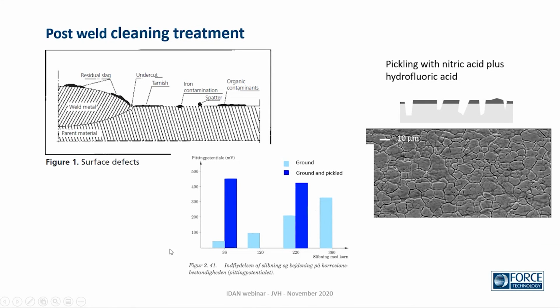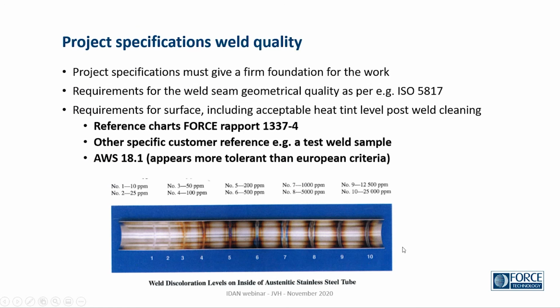But we can see the effect here that we have very good corrosion resistance when we pickle. If we only grind to get rid of the oxides, then we would not get as much. The finer we grind, the better it gets, but still not the same as pickling to solve the problem.